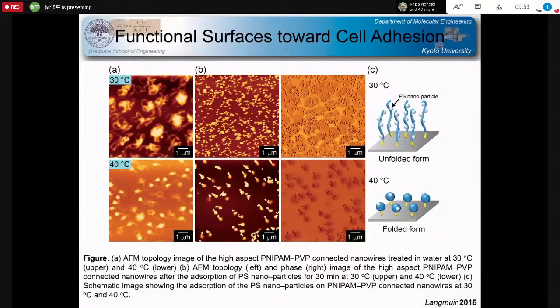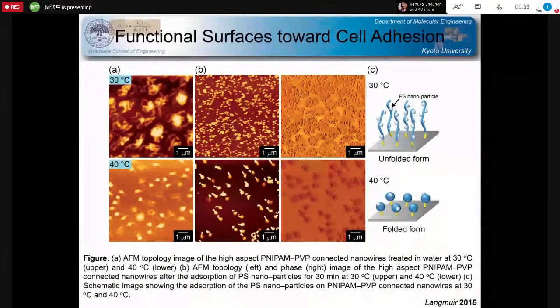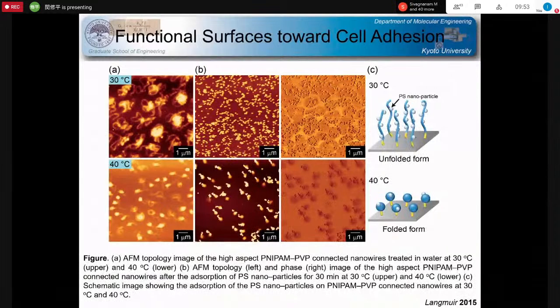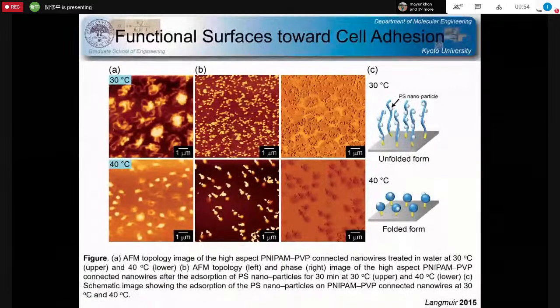And such kinetic behavior was also observed in the interaction of the nanowires with nanoparticles. In this case, we are using polystyrene nanoparticles. As you know, polystyrene is a very well-known synthetic polymer material, and its surface is strongly hydrophobic. So the hydrophobic form of the nanowires has a high affinity to the nanoparticles. After the interaction of the nanowire with the nanoparticles, as shown in this viewgraph, the nanoparticles are clearly fixed onto the substrate. And again, once you cool down the substrate, the nanoparticles are released.